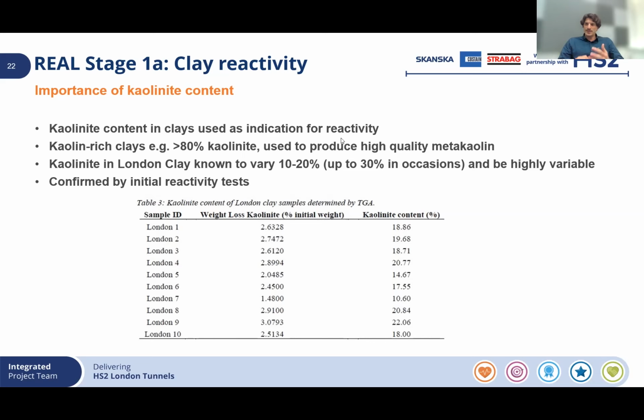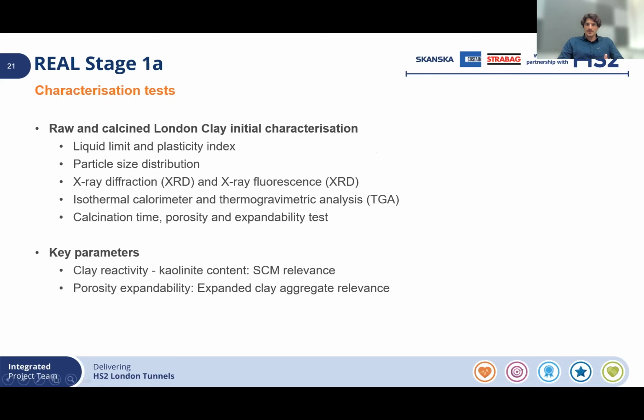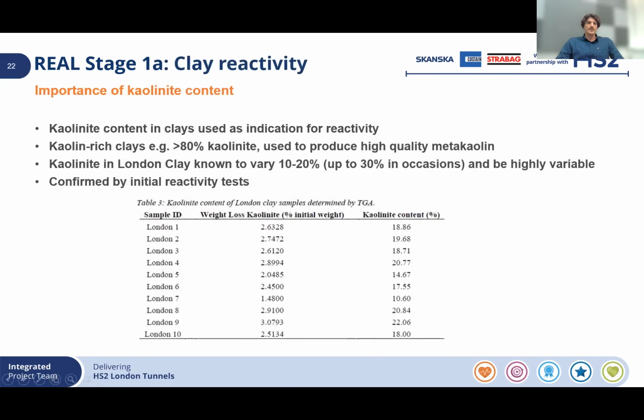So the key parameter for supplementary cementitious materials for clays is the kaolinite content, because this is an indication of the reactivity of the clay and how feasible it would be to use the clay in concrete. The parameters which are key to expanded clay aggregate production are porosity and expandability. So now we're moving to the next slide, where we see some of the first results that we obtained a couple of years ago.